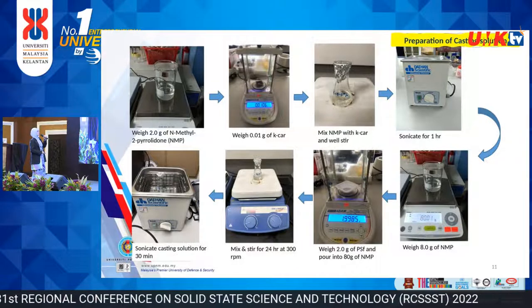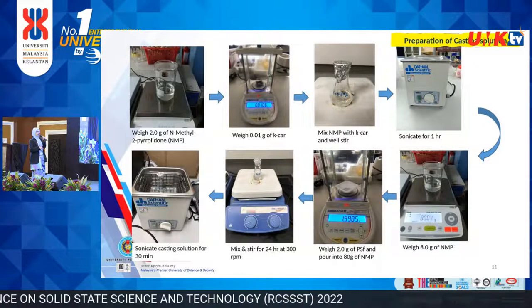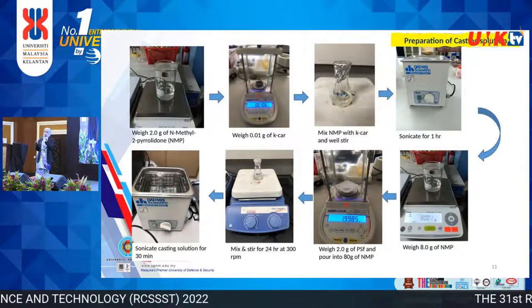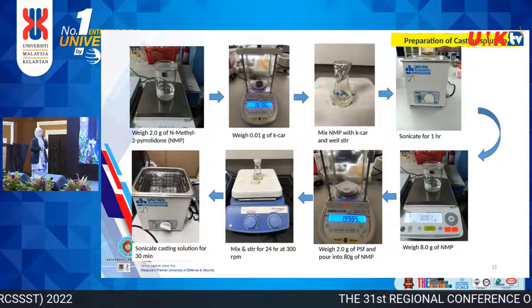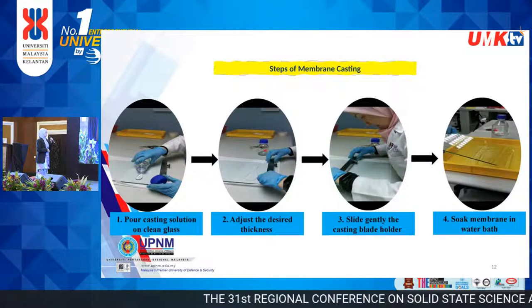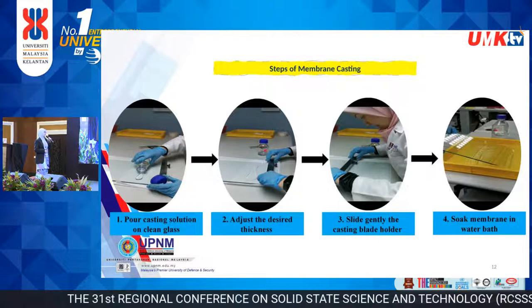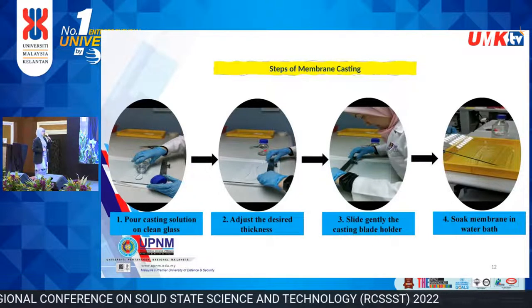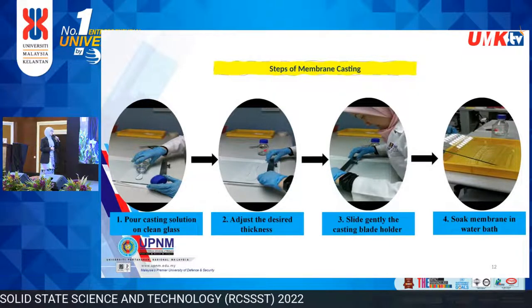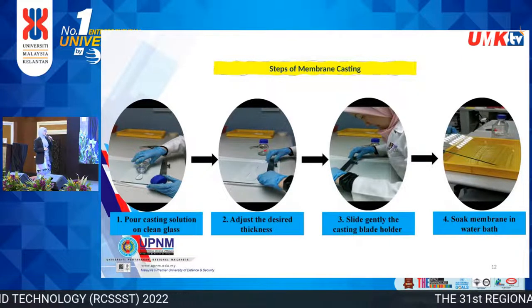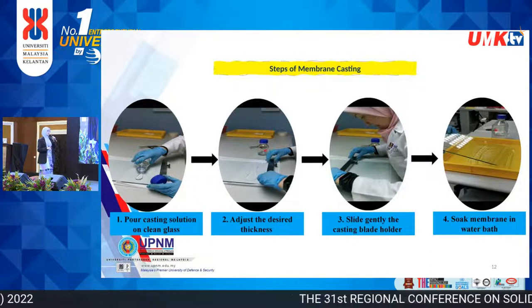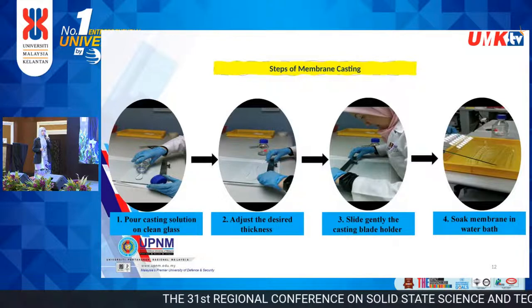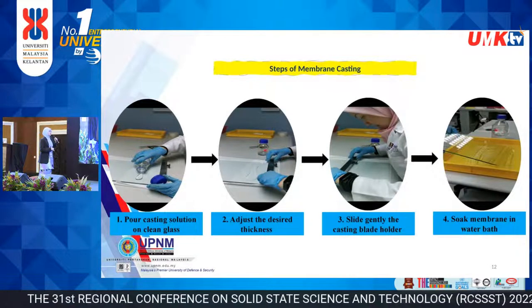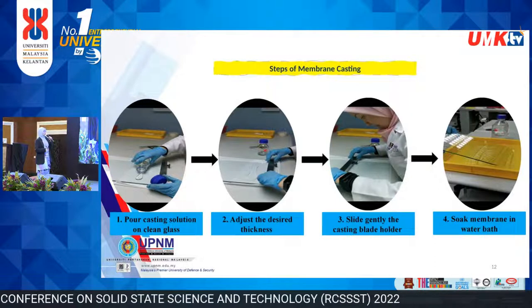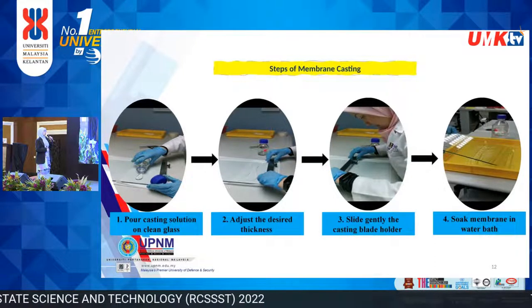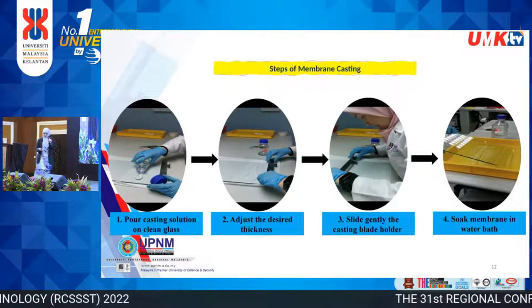All right, so this is the step of casting the membrane. We pour the casting solution, prepared the day earlier, on a clean glass, and then we adjust the desired thickness. For our study, we fix the thickness at 0.2 millimeter. We have a casting blade holder here. The membrane we prepare is manually prepared, and then it is soaked in the water bath. This method we call the wet phase inversion method.